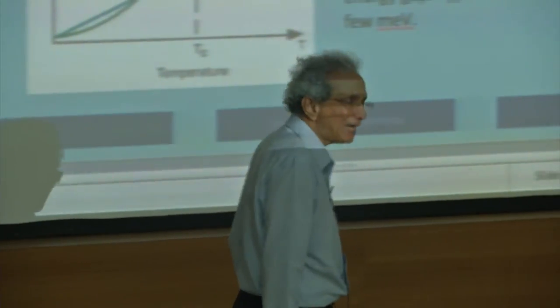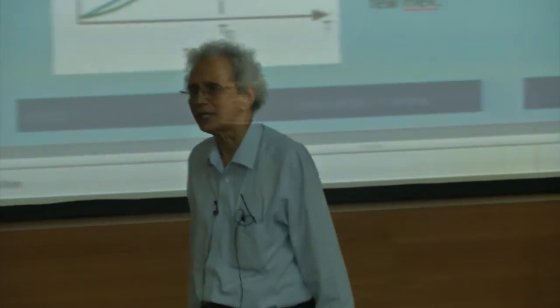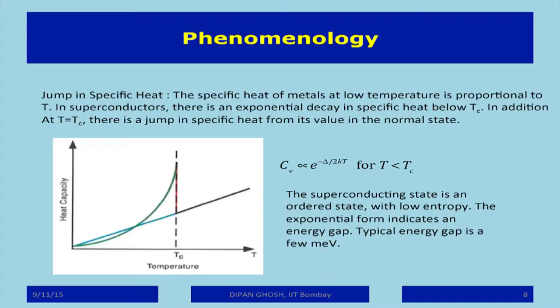And it was known that in a material where the specific heat decays exponentially, that happens because in the electronic energy spectrum, there is a gap. There is a gap between the filled states and the nearest unoccupied state to which the electrons must be promoted in order that they can carry entropy and things like that. So this was our indication that the superconducting spectrum had a gap. A typical energy gap is not very large. Typical energy gap is a few milli electron volts, and that is the reason why superconductivity gets easily destroyed at very low temperature. Because as you know, room temperature is just about 25 milli electron volts, and we are talking about energy gaps which are much less, typically single digit values.